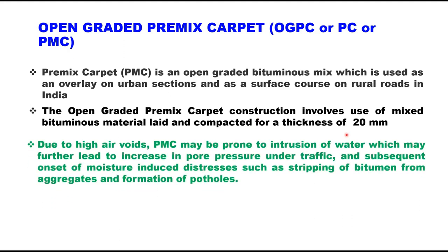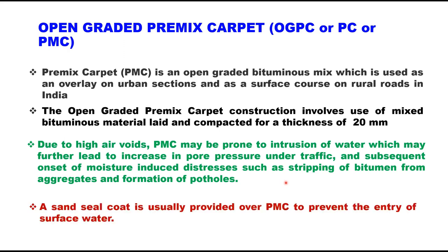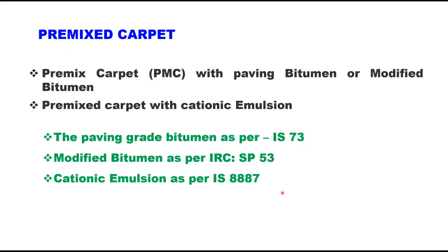Due to high air voids, PMC may be prone to intrusion of water, which may further lead to increase in pore pressure under traffic and subsequent onset of moisture-induced distresses such as stripping of bitumen from aggregates and formation of potholes. Therefore, a sand seal coat is usually provided over PMC to prevent the entry of surface water.